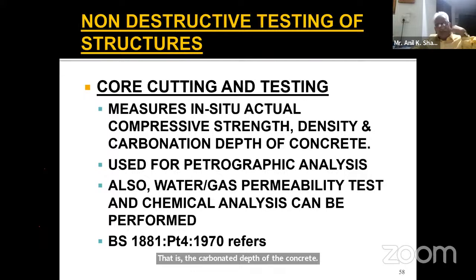So we are able to measure the strength of the concrete. We are able to visually see the texture of the concrete, and using petrographic analysis, we can do actual microscopic examination of the surface of the concrete. Then also we can determine the water and gas permeability by taking out slices of concrete from the core. And using the powder of the concrete core, we can also do the chemical analysis of the concrete which has actually gone into the construction.